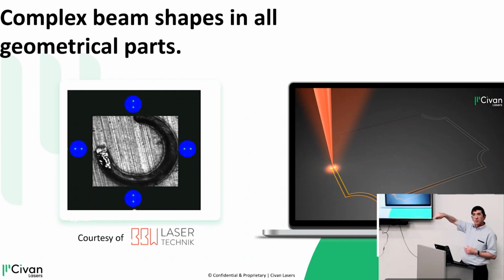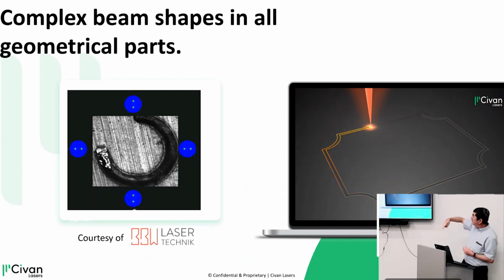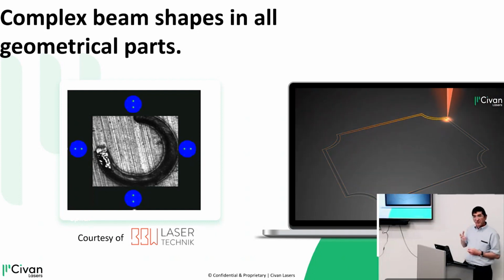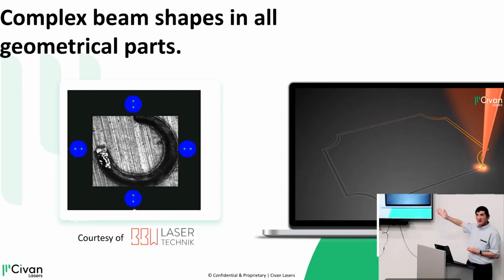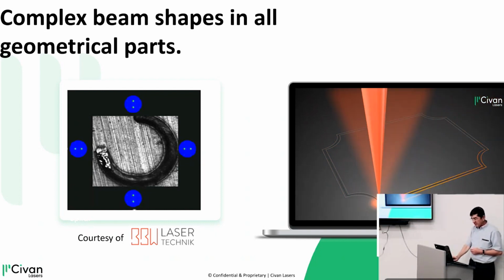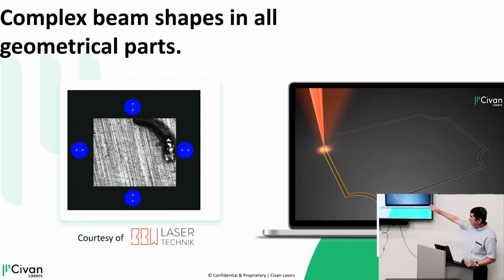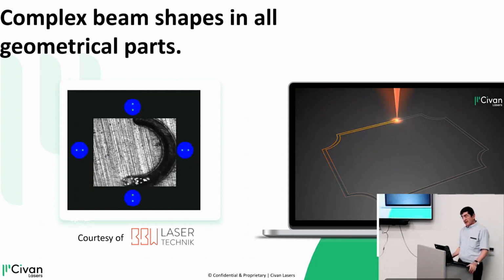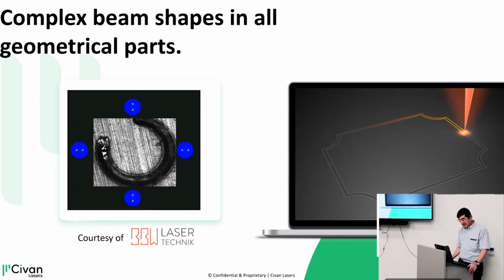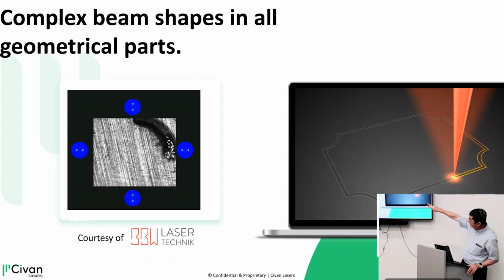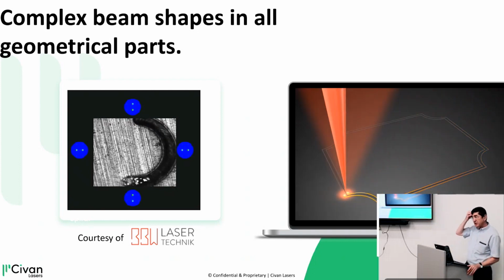If you print, let's say, 2 meters per second, you have to change the orientation at a huge speed. You cannot do it with mechanics. But of course, electro-optically, you can change the orientation whatever way you want and very, very fast. And what you see on the left is actual fast camera where you can see 2 points, and as they go around, the orientation changes.